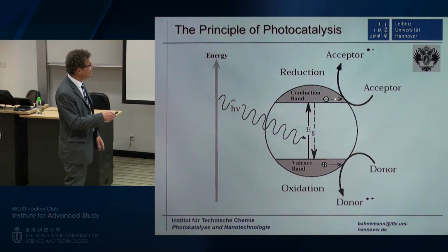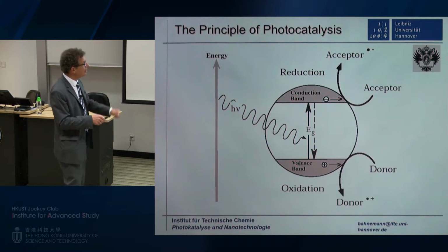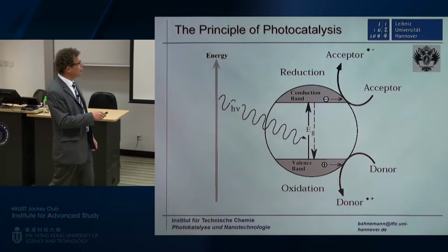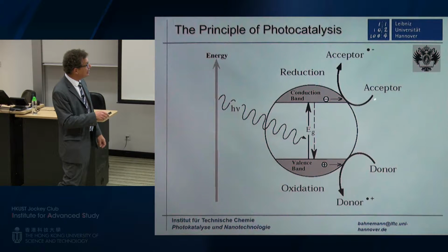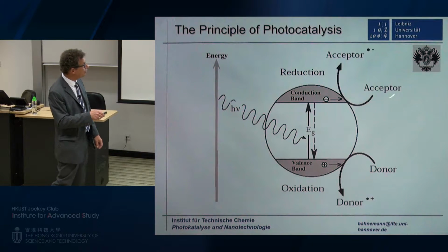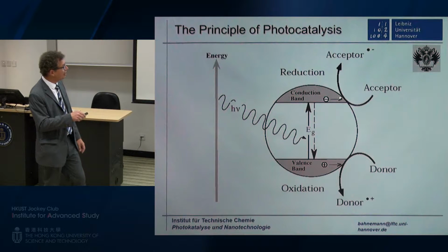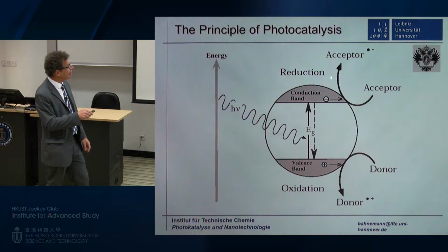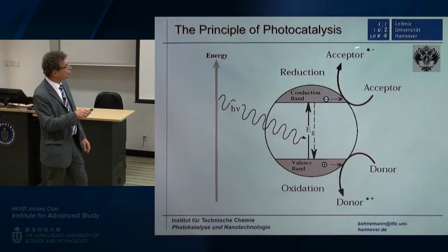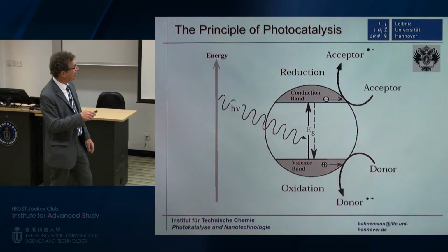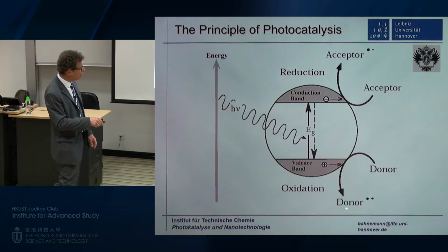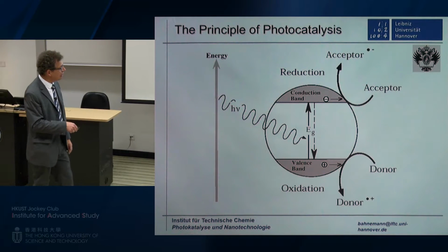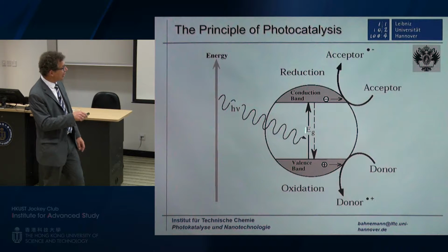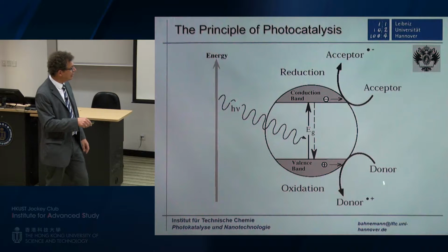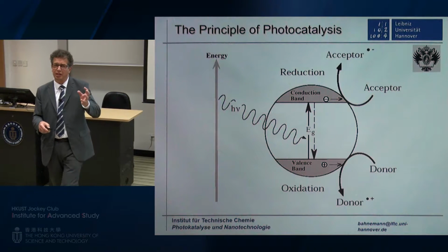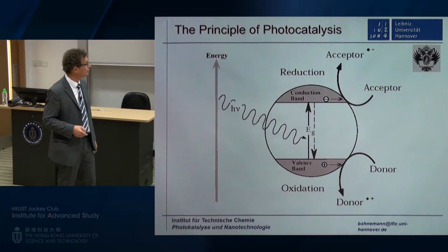The only difference being that the charges are not used to generate electricity, but the charges are used for chemical reactions. If you have an acceptor, usually adsorbed on the surface of the nanoparticle, then this acceptor can accept an electron, becoming in the first step reduced to the respective radical anion, while a donor donates an electron and becomes oxidized to the radical cation. So one photon, if it's active, can generate one radical cation and one radical anion. That is the chemistry that is initiated by photocatalysis.